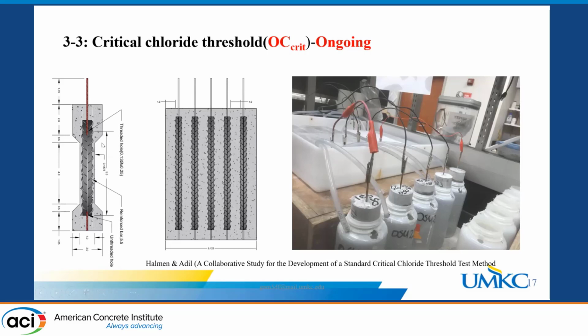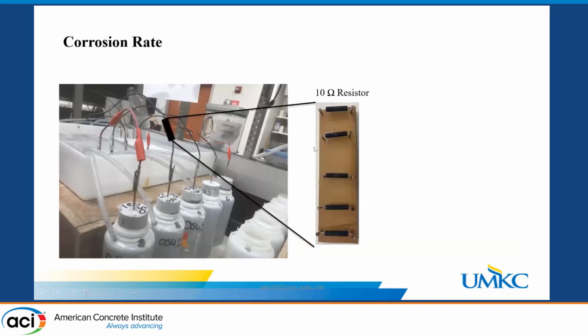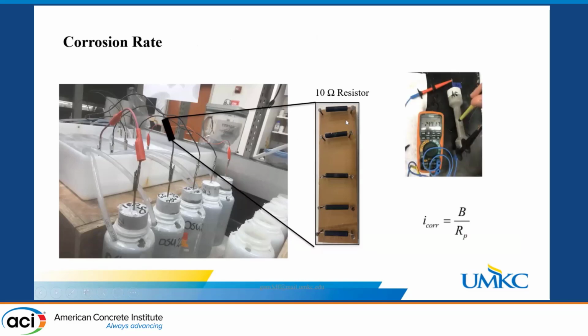So I cast them again, and right now it's ongoing. That's why I wrote it's ongoing. For next time, we are designing to immerse them in lime water for at least 48 hours, so that the specimens get saturated again before we introduce them into the salt solution. And as I mentioned, after we cast them, we decided to modify things a little bit, and we are going to install a resistor between the anode and cathode to monitor them and find out whether the penetration sealer affects the corrosion rate as well or not.